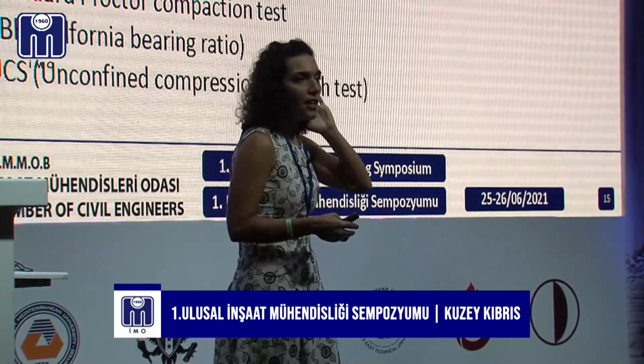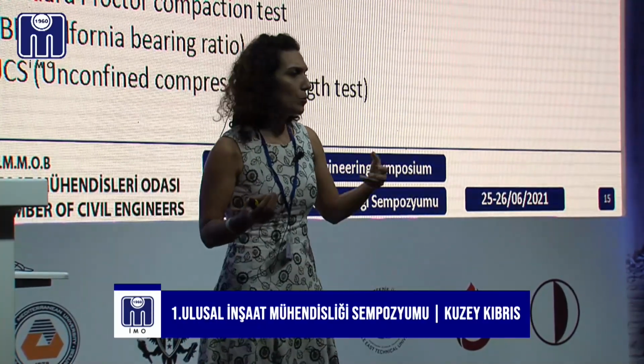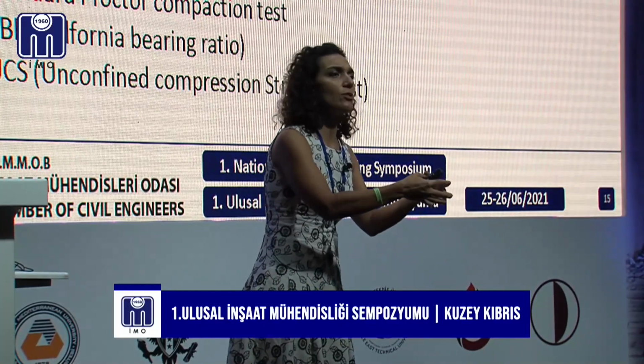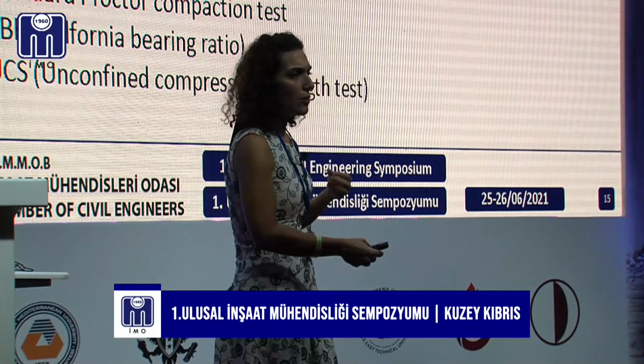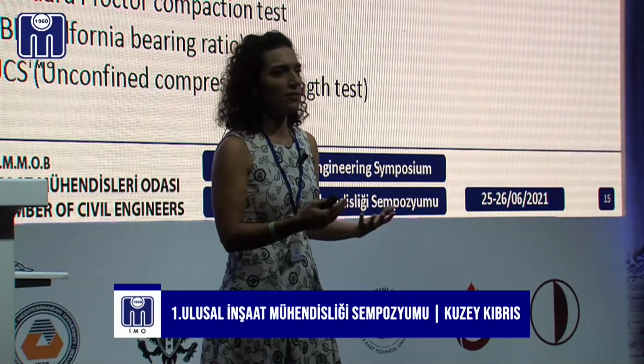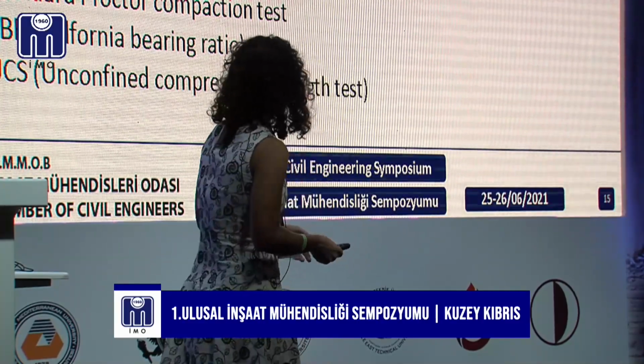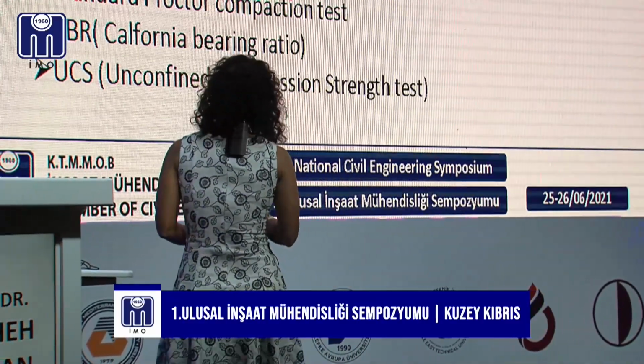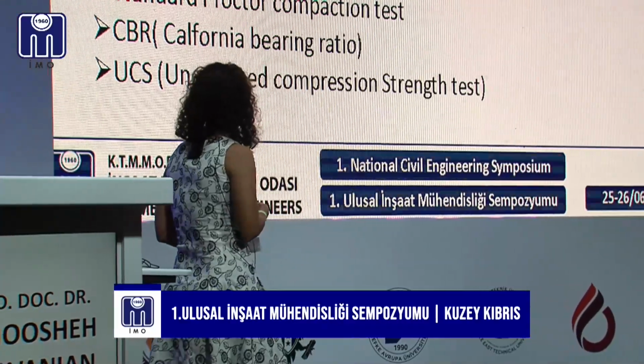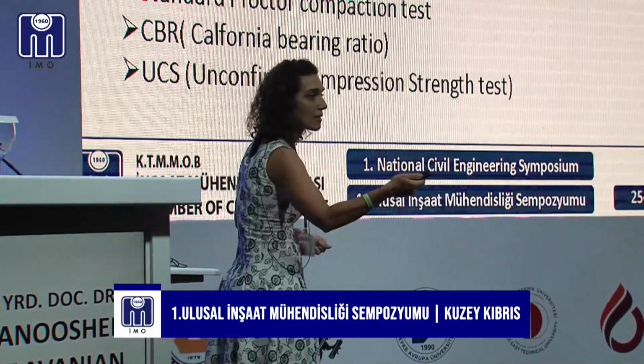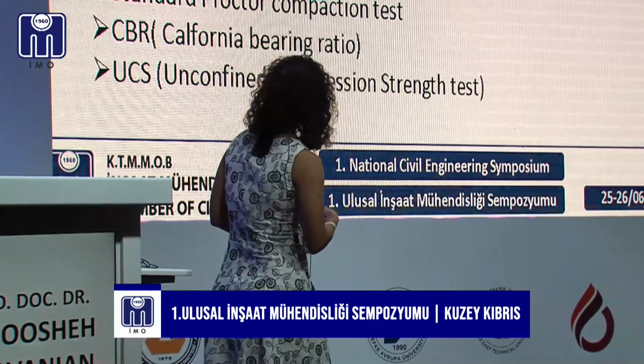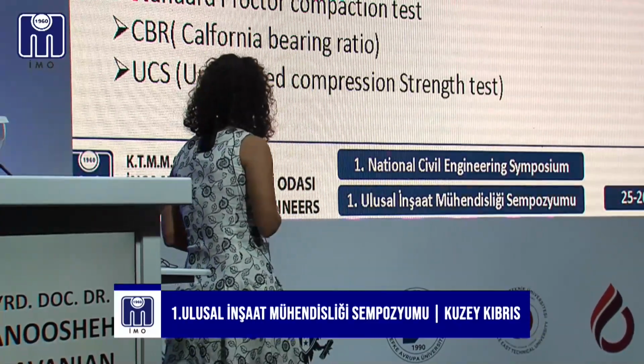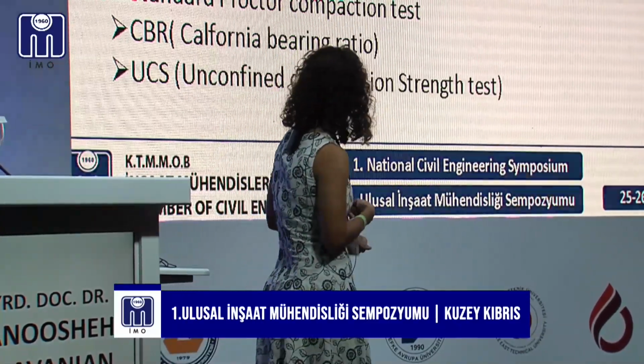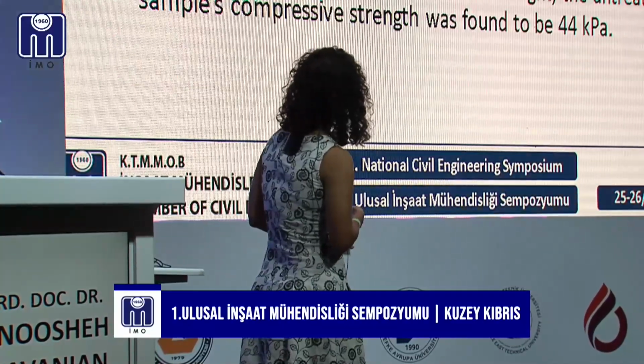That was not too expansive, not too stiff, something normal, average, that we can see in most of the areas. We want to see what is the effect of this plastic bag on this. So the tests that were performed were Atterberg limits, like basic, to see which kind of clay we have, standard Proctor compaction test, CBR, and unconfined compression test.